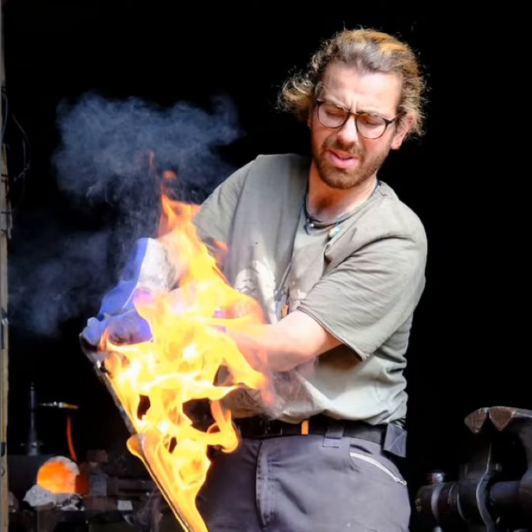very, very thin stock, because then it doesn't really stick on the outside, and maybe I have to remove 1 or 2 layers from the outside, and in the center it's stuck together. But then you basically have to use more heat with wrought iron. You don't lose the carbon if you overheat it, so that's not a problem. You just add a lot of heat and in my case a lot of borax flux, then you stick it under the hammer, and usually it holds up. And then you fold it a couple more times. After that, there are not really delaminations anymore in the wrought iron. Usually you can forge weld it back together, even if it's really, really dirty.